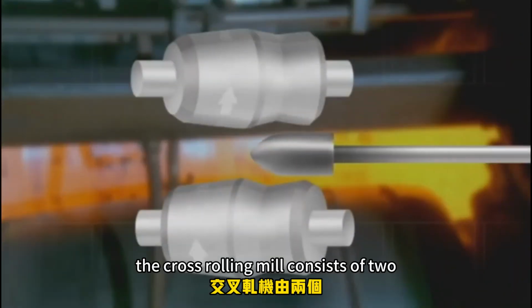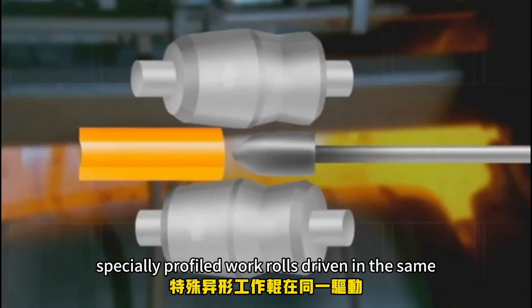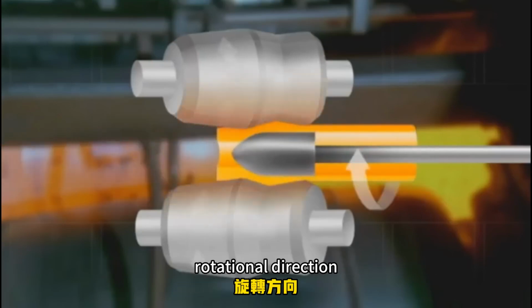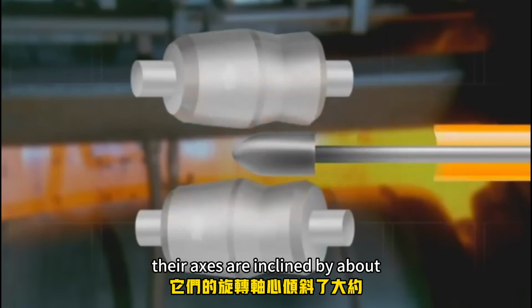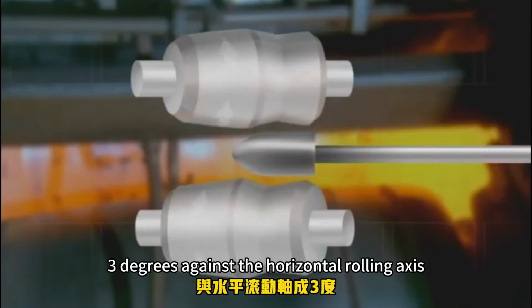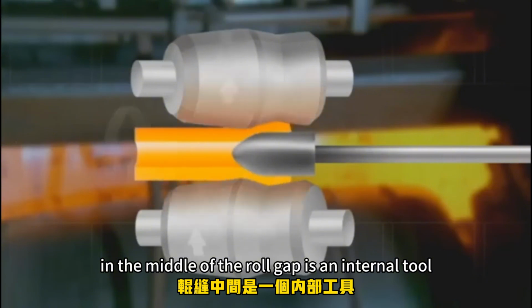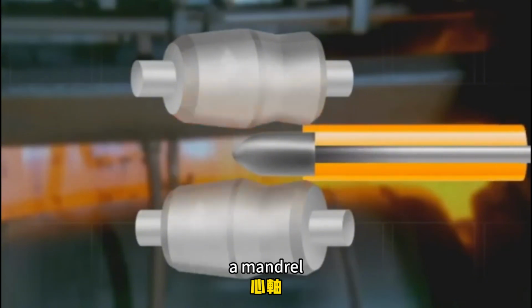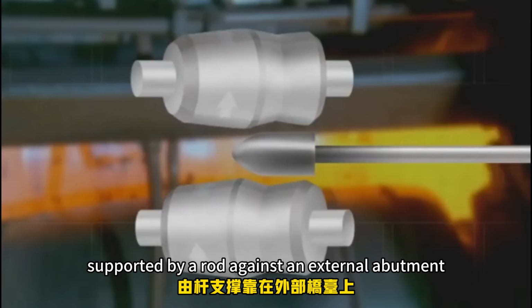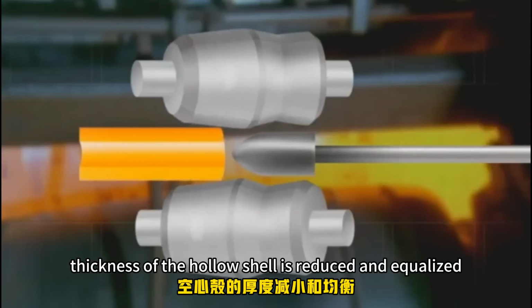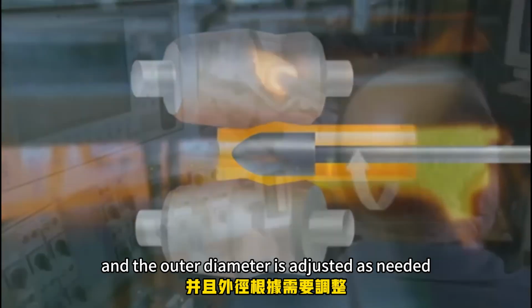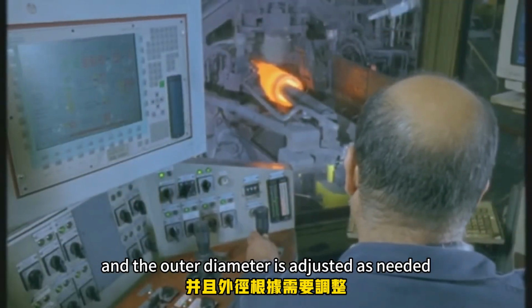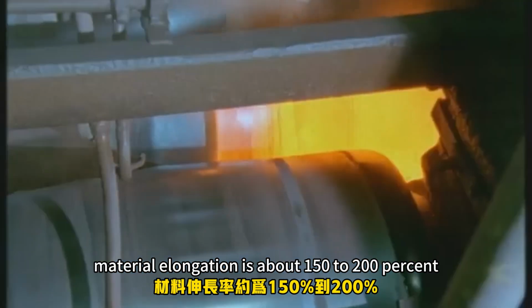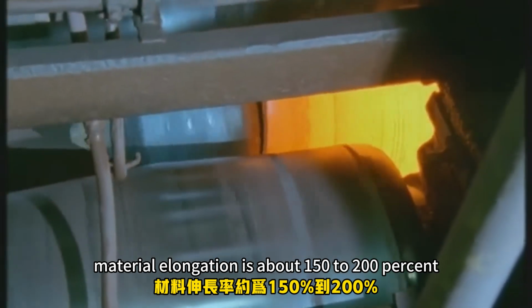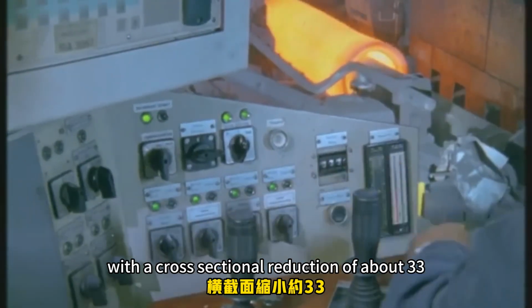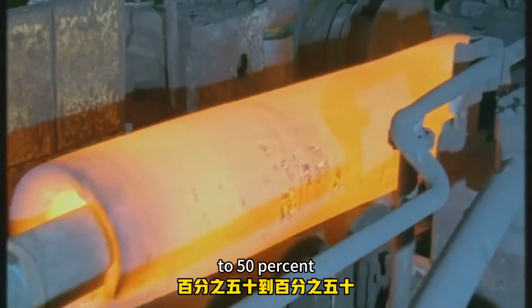The cross-rolling mill consists of two specially profiled work rolls driven in the same rotational direction. Their axes are inclined by about 3 degrees against the horizontal rolling axis. In the middle of the roll gap is an internal tool, a mandrel supported by a rod against an external abutment. The wall thickness of the hollow shell is reduced and equalized, and the outer diameter is adjusted as needed. Material elongation is about 150 to 200%, with a cross-sectional reduction of about 33 to 50%.